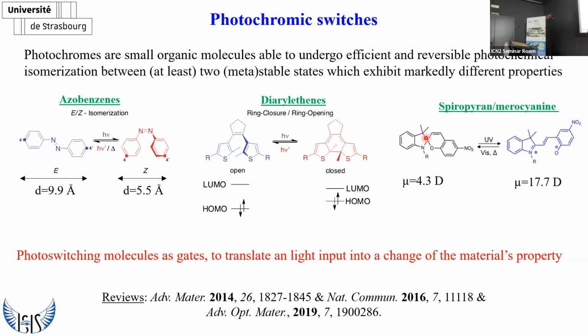metastable. Or, with the diarylethene, you can switch from the open to the closed state with UV light and go back with visible light. What is peculiar here is that the 2 states are thermodynamically stable. And the third one, spiropyran, you can switch from the spiro to the mero form with UV light. You can go back with visible light or thermally. Here you can see that there is a major difference in the dipole moment in the spiro versus mero, whereas the major property that is changed in the diarylethene is the energy level. And here there is a bit of change of dipole moment, but there is also a big change in the conformation of the molecule.